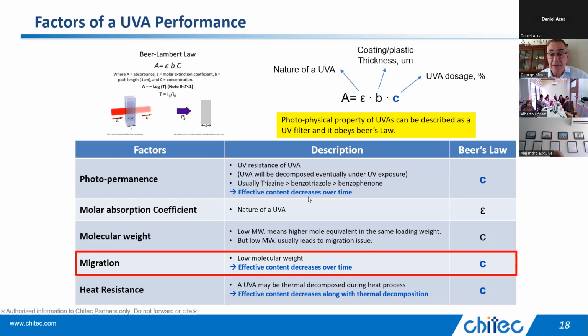Heat resistance, especially if it's a baking enamel, but also you have to be a little bit worried, and this is really important in Mexico. You get some bright sunlight. A car in Cleveland, Ohio, which is of course much further north than Mexico, gets all the way up to 180 degrees Fahrenheit surface temperature. So you can hit 70, 80 degrees C fairly easily. And when you do that, you can boil a UV absorber out if it's not a big molecule or if it's not reacted into the film.